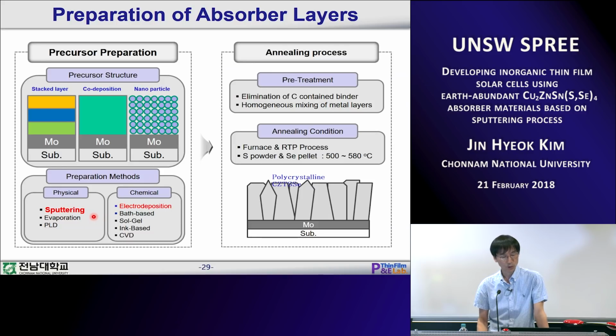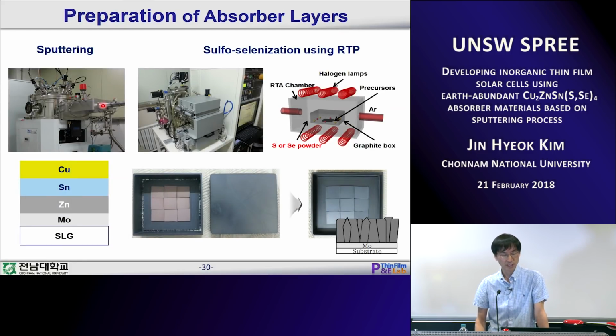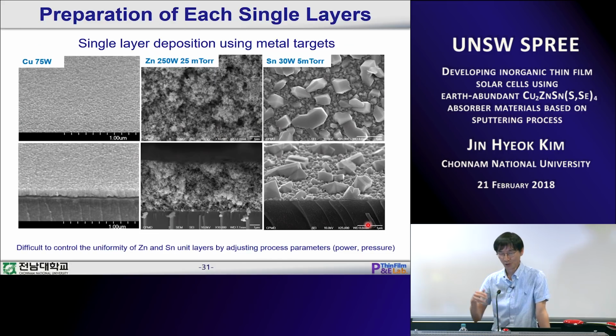A long time back, we also did electrodeposition, but now we are much more focused on the sputtering process. To prepare the precursor layer, we prepare a stacked layer, and then do the sulfo-selenization process. Finally, we have this polycrystalline thin film absorber material. To do that, we use this sputtering machine and make this stacked layer. We put zinc first, then tin and copper, and do the sulfo-selenization process using an RTP machine. And then finally, we have this kind of absorber layer. But to do that, there are many technical issues to optimize. So I cannot explain in detail.